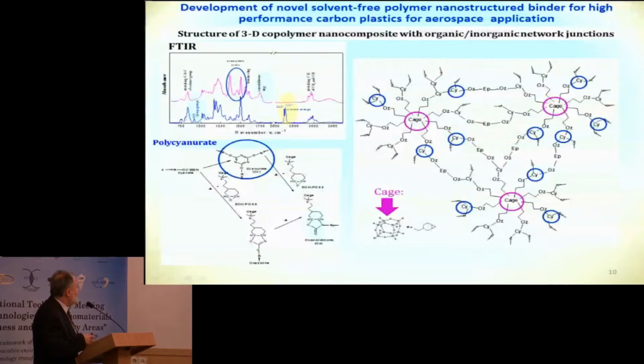And what are the advantages of this material? No use of toxic organic solvents, zero porosity of carbon plastics, high mechanical performance up to 200 degrees at long time service and up to 300 degrees short time service, as well as at high humidity. And we can play with the composition to correct the properties. Lower binder content in carbon plastics, which gives lighter aerospace constructions by 8–10%, and a significant improvement effect without changes in technology, because manufacturers would like to get something new and better without any serious changes in technology. This is important.